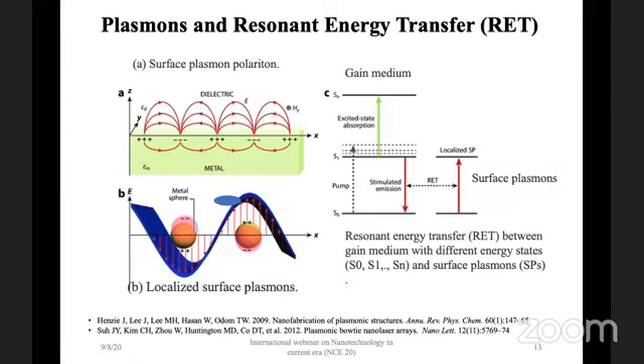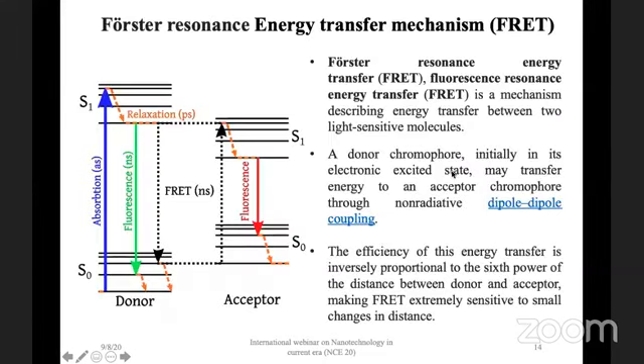Not only plasmonic lasers, but this is also being used to transfer information from one side of a conductor to the other side of a conductor, with quantum dots attached on both sides, using plasmonics. So that's a very important phenomenon. We need to have resonance. Now what we can do is either excite plasmons and then transfer energy from plasmons to the gain medium, or excite the gain medium using a laser and then transfer energy to excite the plasmons. Both ways this can be done.